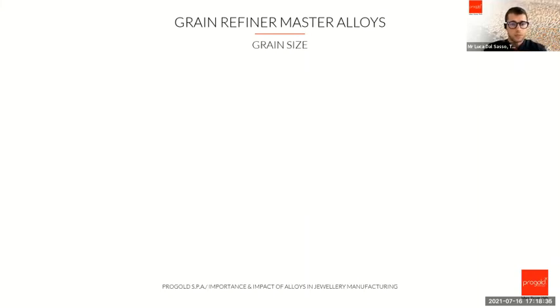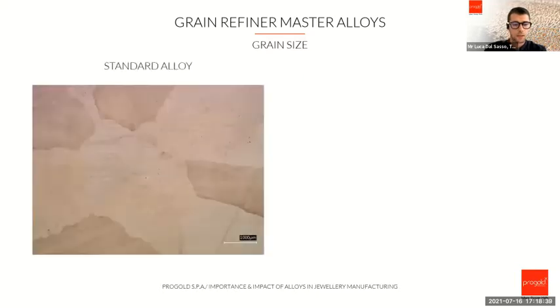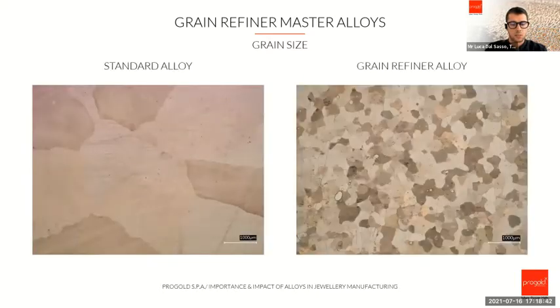Starting from the grain refiner master alloys, the first thing we can talk about on these master alloys is what? The grain refining master alloys allow us to have a very, very fine grain microstructure. On the left side, you can see standard alloys without grain refiner, and as you can see from the marker, the grain is over 1000 micrometers. So the grain is considered very big. On the right side, we have a grain refining master alloy that has a grain size of about 250-300 micrometers. So you can see how big the difference is between one and the other.